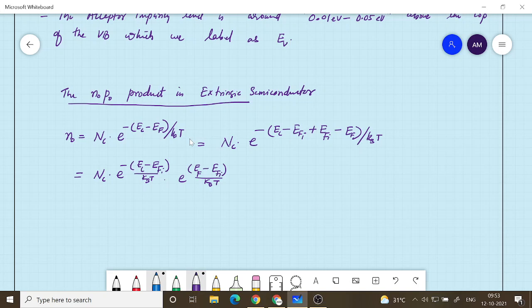kBT here also. Now if you look at the first term, NC into e raised to minus (EC minus EFI) by kBT is basically defined as Ni, which we earlier found, because in the original expression, if it is an intrinsic material, the Fermi level will be called EFI. So if you replace EF with EFI, the concentration of electrons is called the intrinsic concentration. So I am substituting that into e raised to (EF minus EFI) by kBT. Again, I am assuming the Boltzmann approximation is valid, which is a good approximation if the Fermi energy level and the bottom of the conduction band are away by a factor of 3 kBT. So under that assumption, I am writing like this.